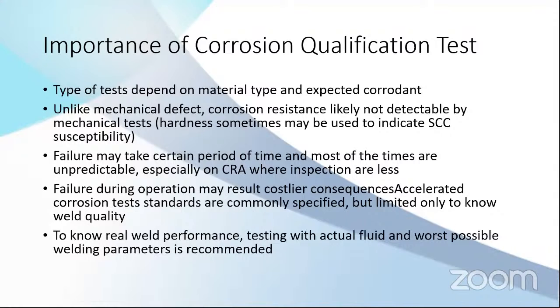And there are a lot of possible corrosion tests. There are different standards of corrosion tests, and most of the standards are only to know weld quality. But if you want to know the real corrosion resistance of the weld, you need to test with actual fluid and the worst possible welding parameters. So you can know the real performance of your weldments, the real corrosion resistance of your weldments.